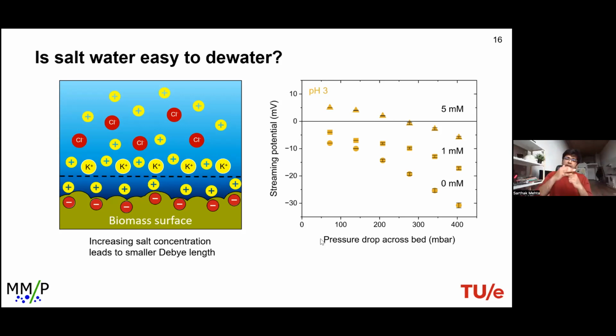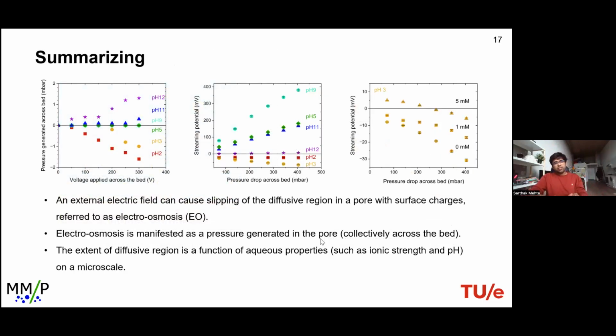This reversal in polarity can be explained by the shielding effect of the ions. Because of a negatively charged surface, the ions are shielded, and because the ions shield the negative charge, at a certain concentration of ions, the diffusive region does not experience any potential from the biomass, but the potential of the shield itself. So instead of experiencing negative charges as it would have earlier, now it experiences a net positive charge, and in doing so, the streaming potential changes. So the reversal of polarity is because of a shielding effect, and the diffusive region now experiences the ions instead of the biomass surface.